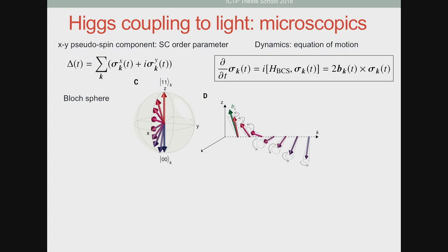So you can think of it as Bloch equations, where the dynamics of this pseudospin is going to follow this Bloch equation, where the Anderson pseudospins are coupled to this effective field, b_k. The orientation of the effective field will be given by the superconducting gap, but also by the value of the vector potential of light, so that you will have a complex dynamics where the pseudospins rotate around this effective field, and the orientation of this effective field depends on k. And the resulting gap dynamics is going to be the sum over all the k of the x and y components of this pseudospin. And this, of course, has to be solved self-consistently because both sigma_k and b_k depend on the superconducting gap.